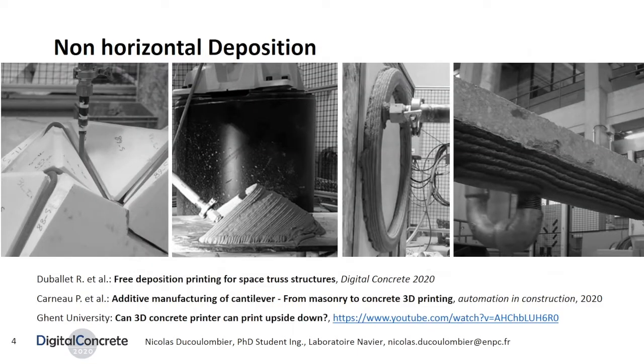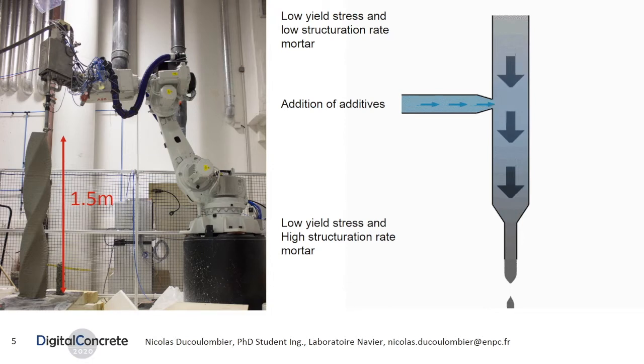In fact, it also highly depends on the support orientation, which can be either inclined, horizontal, or even upside down, as shown in the different pictures. Such yield stress requirements for deposition on inclined supports have been recently studied by Carneau. They are also investigated in the presentation of Duballet concerning a particular fabrication process of a concrete truss, shown in the left picture, that we also highly recommend. There is therefore a need for an inline yield stress measurement at the nozzle level.